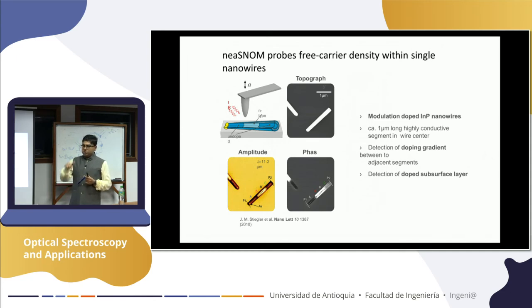As long as you don't scratch it. There's a little physics involved: you have to make sure how far the tip is. You don't want to touch it. You want tapping mode. There are many modes you can do AFM. Tapping mode means you are scanning the surface, tapping continuously with a small gap. You want to make sure there is a small gap, because that's how you are confining the local near field.